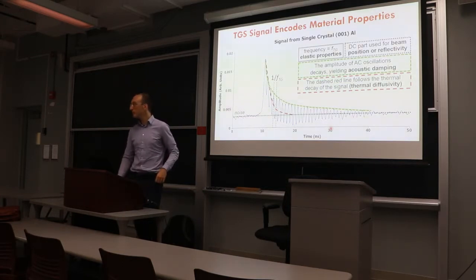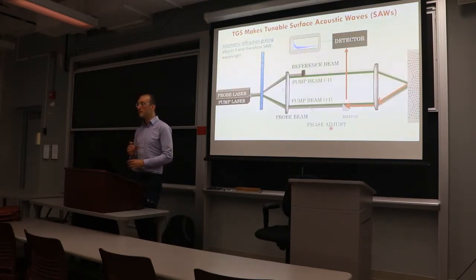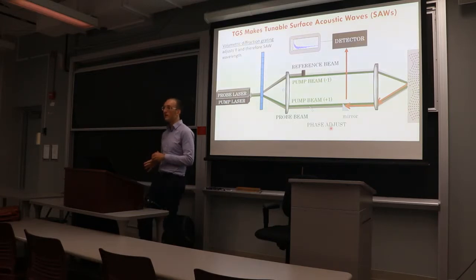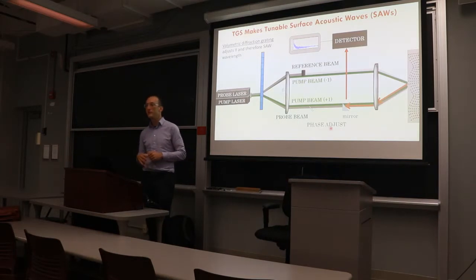Now these might not be the parameters that you want to measure directly, but if they correlate with void swelling or other stuff, then you can use them as fast indicators of what's going on. And you can tune this probe to measure different depths in the material, and this is where it's really well suited to ion irradiation. Depending on the energy of your ion beam, you might be able to penetrate somewhere between 1 to 10 microns into a material.